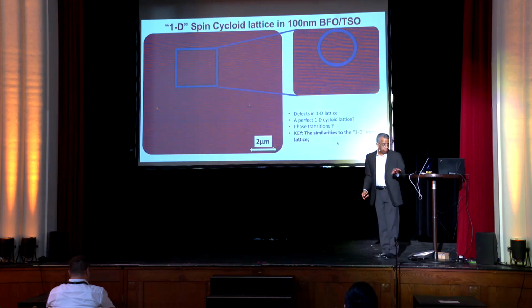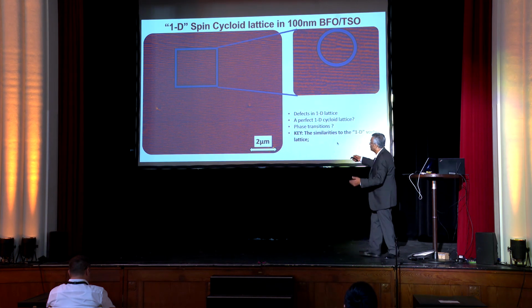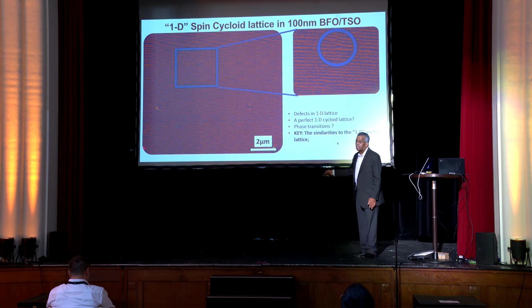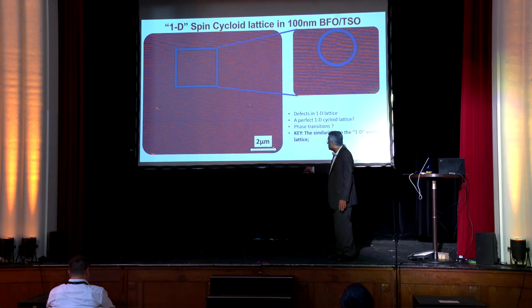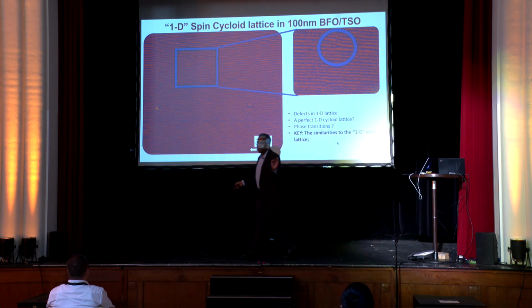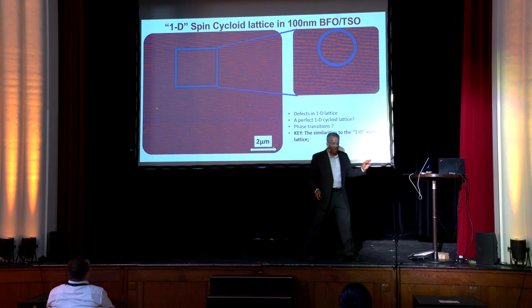And that's shown here in this image. It took a while. It took about 2 weeks to get this image. It's a 10-micron scan of this lattice. And you can see that it's essentially a 1D lattice. But if you focus hard enough, you can start to see dislocations in that. It looks almost exactly like the parallel universe of the vortex lattice that I showed you maybe 5 minutes ago.